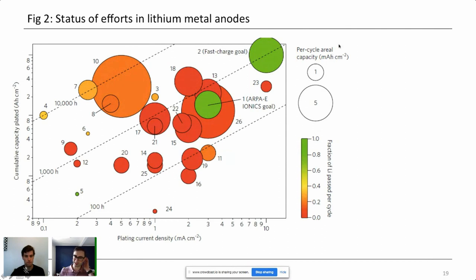So normalized per area, a smaller circle is less battery capacity. A larger circle is more capacity. And as I'll describe later, this is really key to enable a long-range electric vehicle. If you're down here on these small circles, then the inactive fraction of the battery is going to be too large, and you won't have a high energy density that will enable a long range for an electric vehicle. What you need to do is get towards these larger circles, that is, larger capacity of the battery.